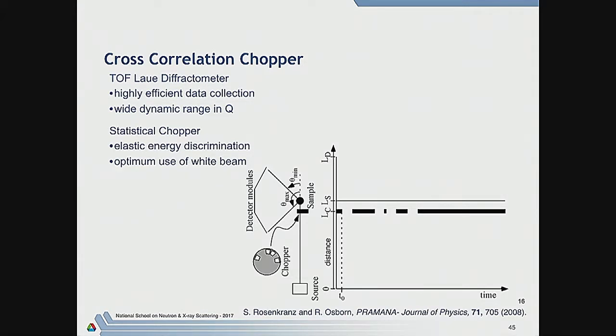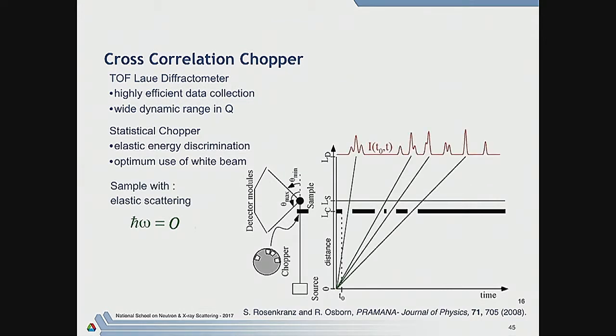So what happens when the neutrons get produced? You then get, as in any white beam technique, a whole distribution of wavelengths being produced, and some of them get through these slots and others don't. So if you have an elastic peak, then here's where the sample is, at LS, just behind the chopper. Then these neutrons will go through the sample and come out at the same velocity. Might get scattered in angle, but they come out at the same velocity. And you get an elastic peak. So you get one here, you get one here, you get one here, you get another one here.